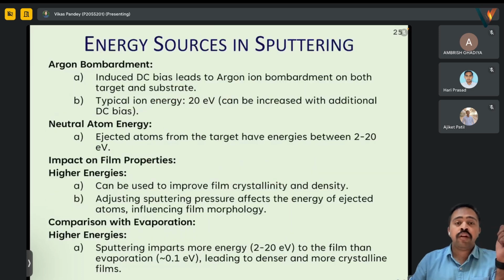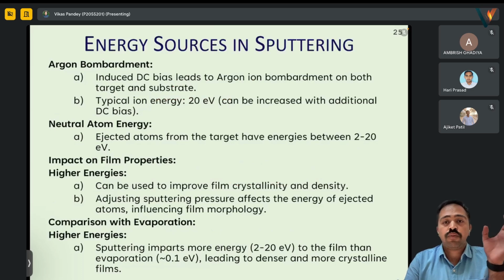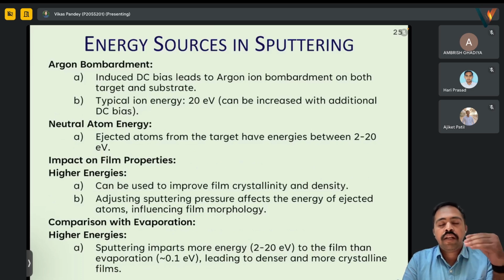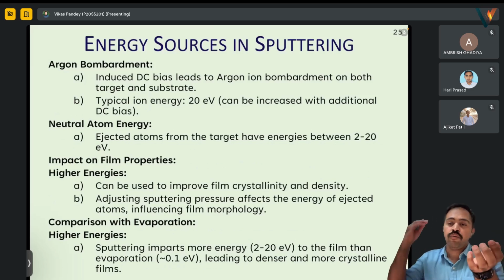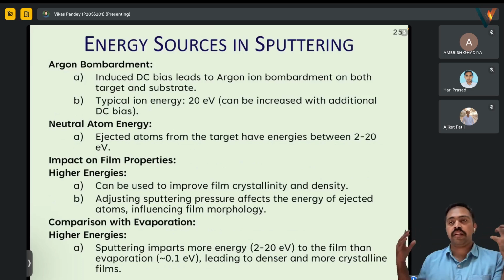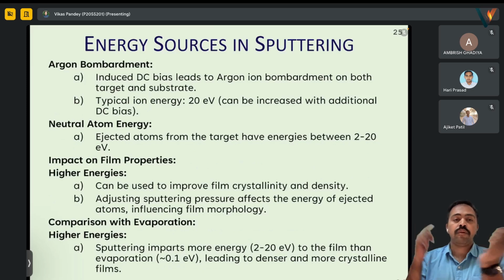So what is the energy source in sputtering? Like in CVD, the energy source was temperature. In ALD, the energy source was plasma. In case of thermal evaporation, the energy source was again temperature, but in the sense of resistive heating. In this case, the energy is neither plasma nor temperature. The energy is due to the argon bombardment, where argon atoms are coming in and bombarding the surface.